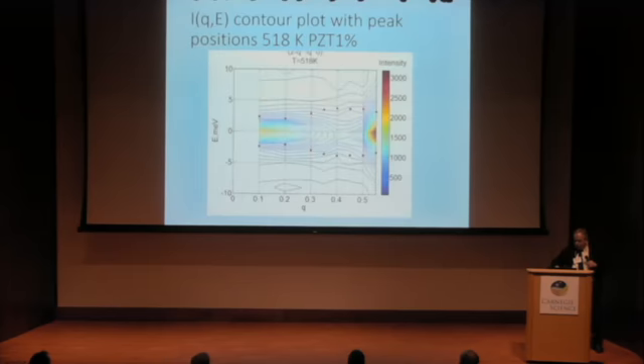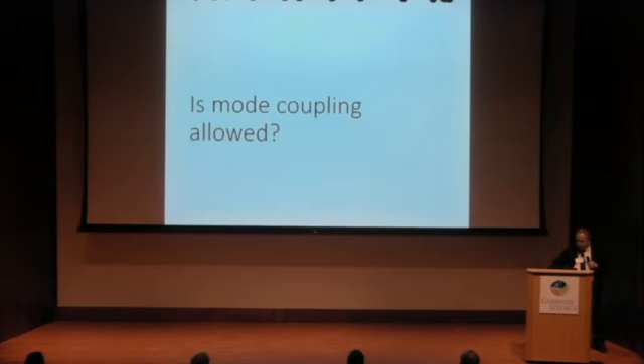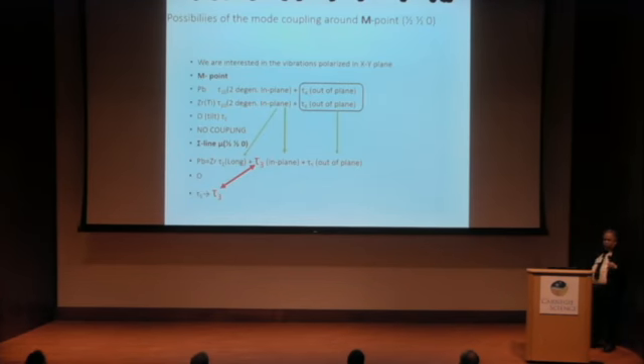This is confirmed by S(Q,omega) measurement. Close to the phase transition, we see the maximum on one side of the endpoint, and we see nothing on the other side of the endpoint. So what can we do? We know from first principle calculations that were published that we expect to have a soft mode at the endpoint exactly. How can it come into play?